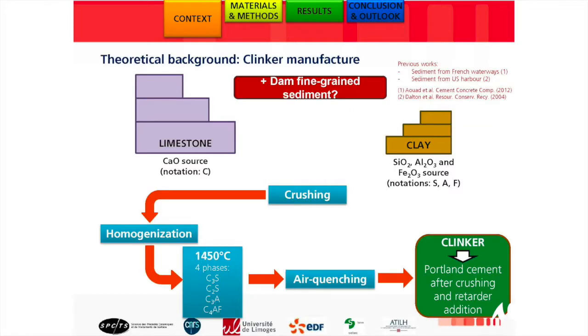Just a quick background on how we manufacture clinker. It's a mixture of limestone, a source of calcium oxide, noted C in the cementitious industry, plus clay, which supplies silica, alumina, and iron oxide, notation S, A, and F. After crushing these raw materials and homogenization, there's a sintering stage at high temperature, 1450 degrees, and we obtain four mineral phases: calcium silicate (alite, C3S), belite, calcium aluminate, and calcium aluminoferrites.